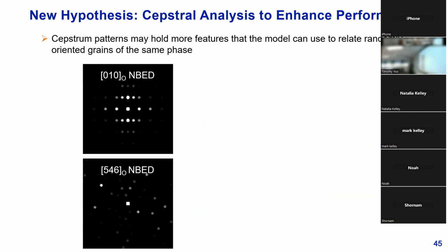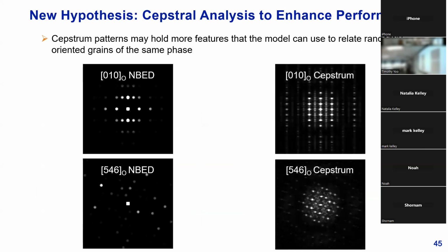But of course, it's probably going to struggle. That doesn't really make a lot of sense. There's not a lot to go off of, no sense of similarity between the two that would help this model function the way I want it. However, interestingly, when we apply the cepstral analysis again here, there wasn't really a huge motivation for this in the beginning. It was just something I was testing and playing around with. We found that by doing so, even though these patterns don't necessarily look the same at all, we can see that as expected, the [010] cepstral pattern retains a high level of symmetry.